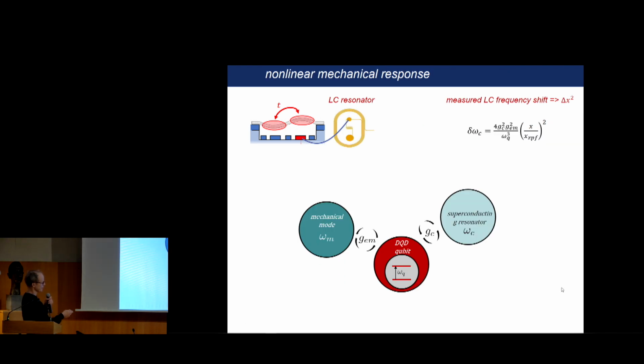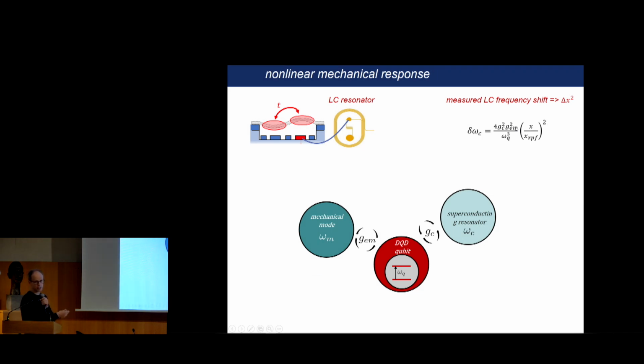So we use the superconducting resonator to detect the vibrations. And so we have here a direct relation between the displacement squared and the cavity frequency. And again, what is interesting is that the coupling strength is large, and this makes us able in this way to detect vibrations even in the quantum regime, so when the displacement is smaller than the zero-point motion.